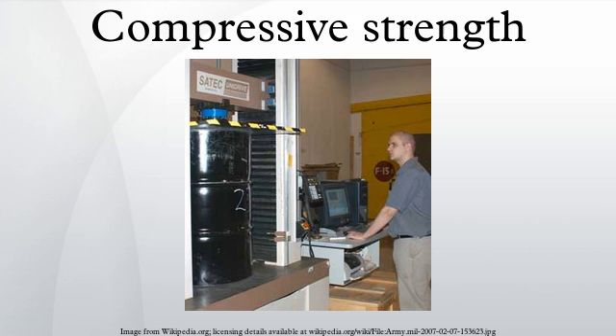On compression, the specimen will shorten. The material will tend to spread in the lateral direction and hence increase the cross-sectional area. In a compression test, the specimen is clamped at the edges. For this reason, a frictional force arises which will oppose the lateral spread. This means that work has to be done to oppose this frictional force, hence increasing the energy consumed during the process. This results in a slightly inaccurate value of stress which is obtained from the experiment.